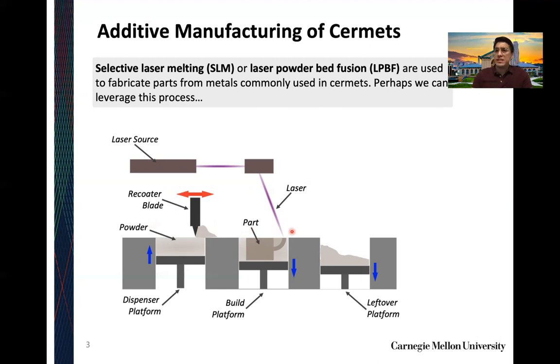And any powder that doesn't essentially get deposited onto the powder bed will then just get pushed into the leftover platform you see here on the right. Afterwards, a heat source in the form of a ytterbium laser comes across, and using sort of a micro-reflecting system, the laser gets directed onto the top surface of our powder bed, thus writing or selectively melting the powder, in the form of the cross section of that particular layer. The process repeats, the build platform lowers again, and it keeps going until you pretty much finish the final layer of your part.